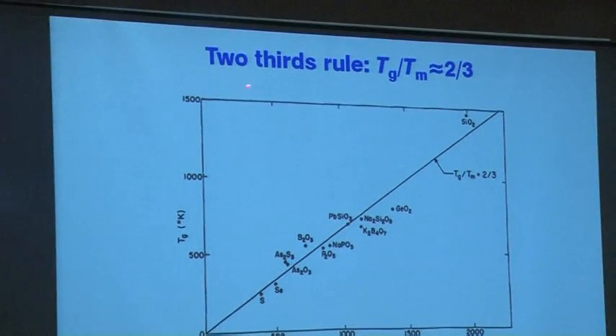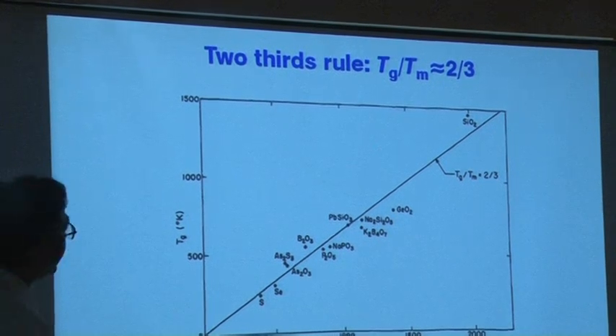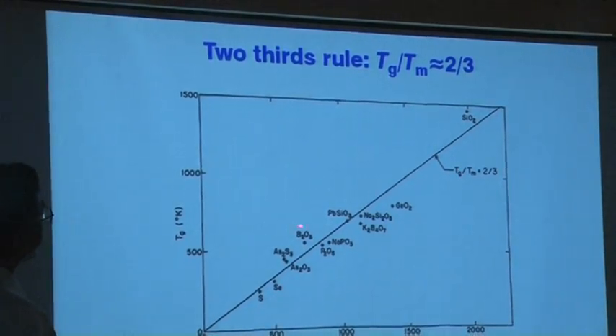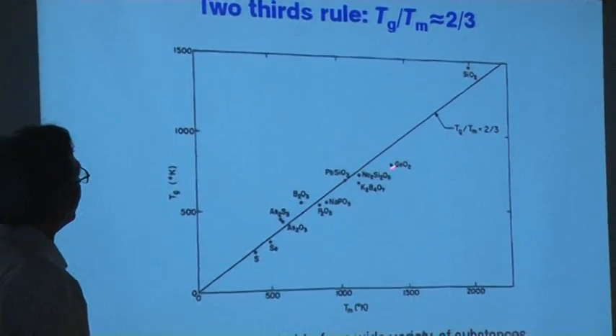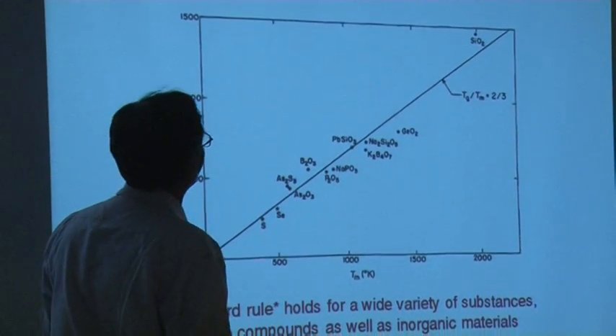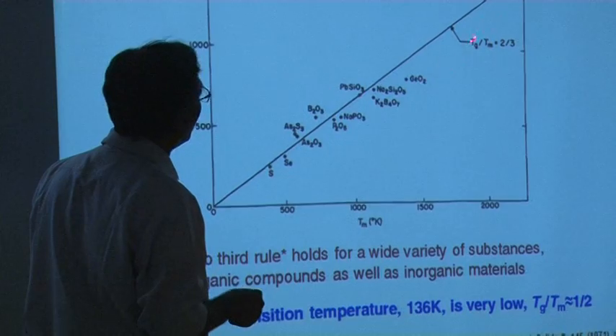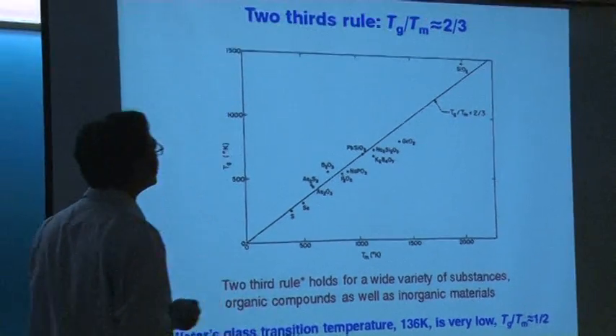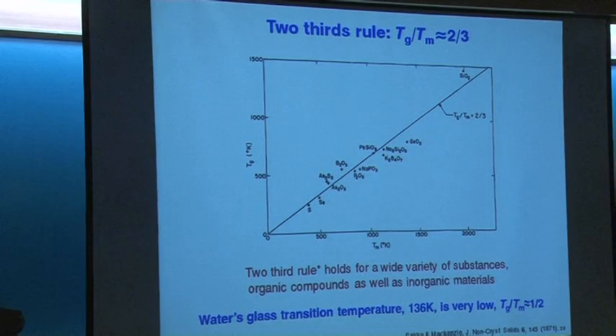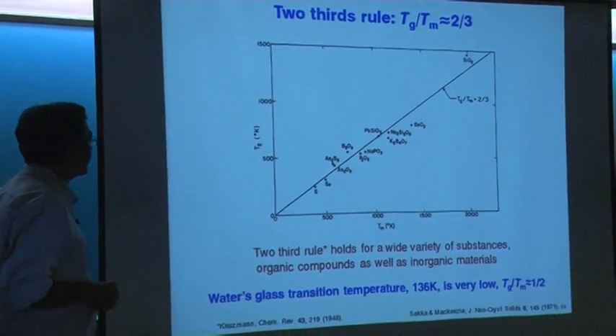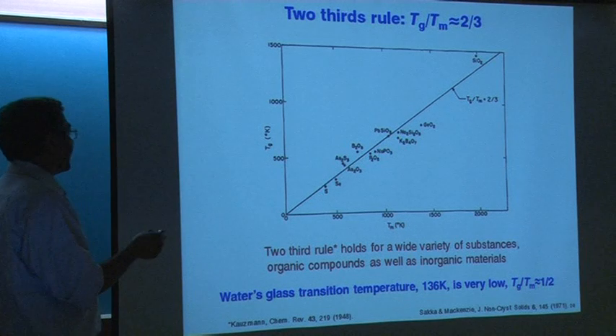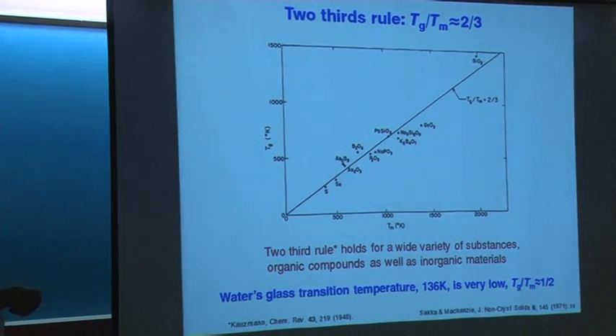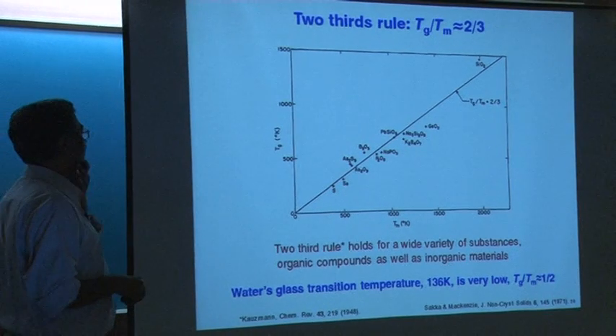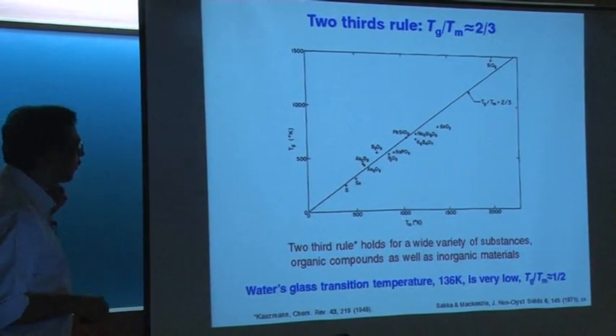Now, there is an almost universal rule followed by all liquids. There are different kinds of liquids. They can be chalcogenides, phosphates, orthoterphenyl, heteroalkali germanium oxides. All of them follow this beautiful rule: the glass transition temperature Tg by Tm is 2/3. This is called the 2/3 rule. So if you know a liquid's melting temperature, you can predict its glass transition temperature is 2/3 of that. Not for water.